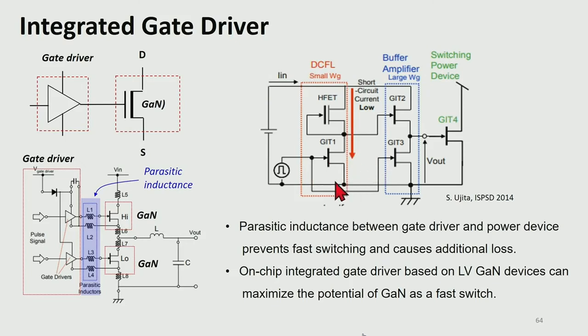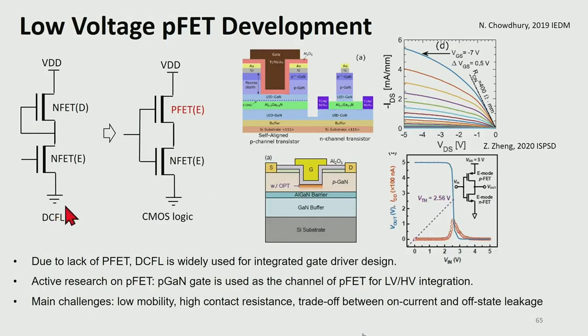And for the gate driver design with gallium nitride, the DCFL, which uses a depletion mode NFET and enhancement mode NFET, is mainly used. But to use a conventional CMOS circuit, we need an enhancement mode PFET. Although there are still many technical challenges to make a good enhancement mode PFET, such as low hole mobility or poor contact resistance, there has been good progress in this area.